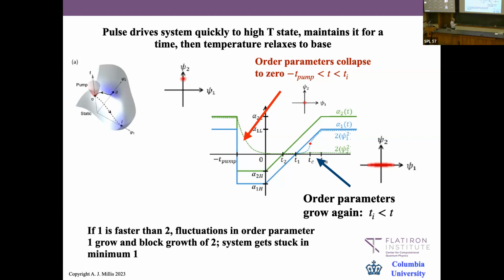At some time, the order parameter first for the more favored one and then for the less favored one crosses zero, and fluctuations of that kind of order start to grow. The magic of this theory is that because there's a cross-coupling term, if there's a sufficiently different time scale, the more favored order parameter grows slowly.